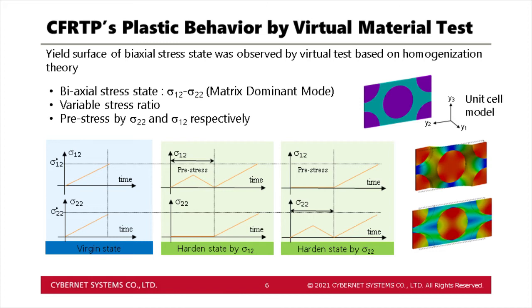Next, I will explain the conditions of the virtual material test conducted on CFRTP. The unit cell model is shown here. The analysis is performed based on the homogenization method. The fibers are oriented in Y1 direction. In this case, we assumed a plane stress state. Then there are three components of stress, but the normal stress for the fiber-oriented component will contribute little to yielding. So we applied only two stress components, which are in-plane shear stress and transverse stress. A conceptual diagram of this stress state is shown in the blue hashed area.